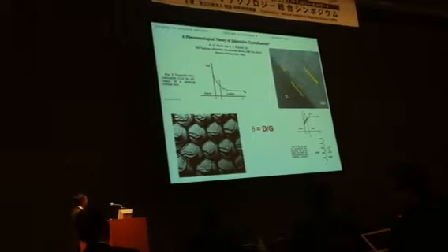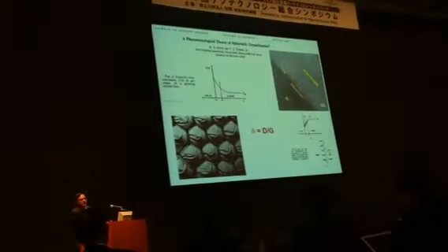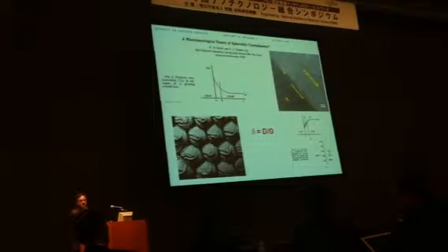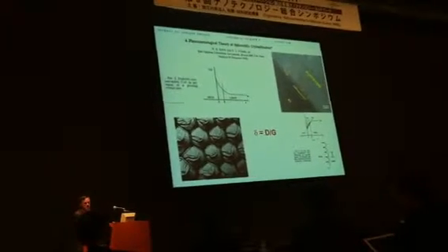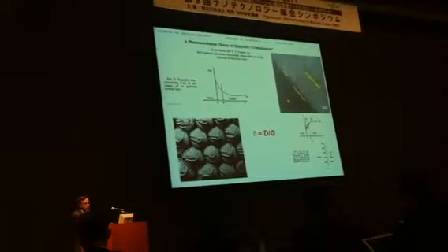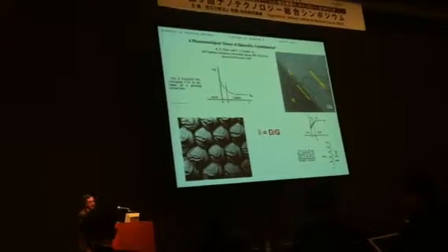If I look at the ratio between the diffusion coefficient and the growth rate, you come out with a length scale. This length scale turns out to be on the order of about 15 nanometers. But that's not the only parameter that's going to be important. The other parameter that comes into play is the nucleation density: the more nuclei I have, the smaller will be the ordered regions. Therefore, I have a means by which I can control the structure and the morphology of these materials.